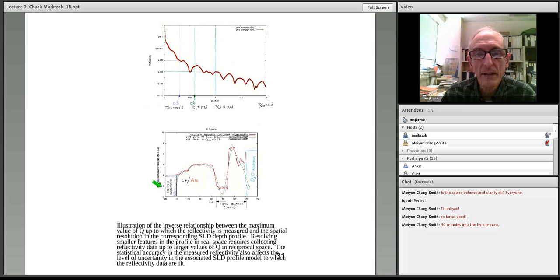So on the left, in this scattering length density profile, we have a silicon substrate that's, again, semi-infinite in extent all the way to the left. There's a chromium pre-wetting layer and a gold film, and then there is a lipid layer chain that's attached to this gold surface via an alkane thiol structure. The bond between sulfur and gold is very, very strong.